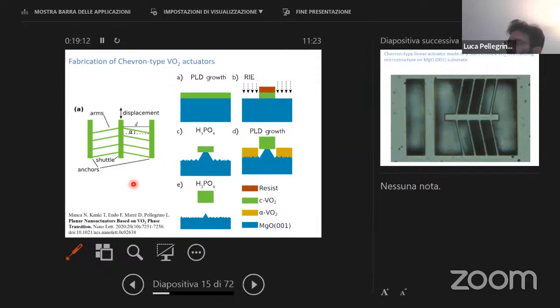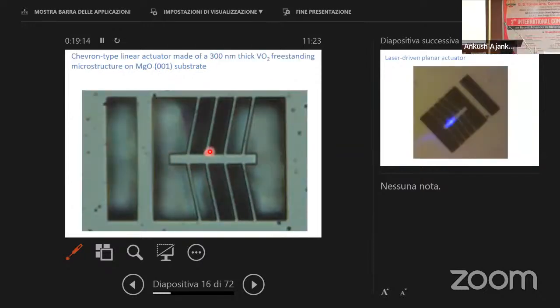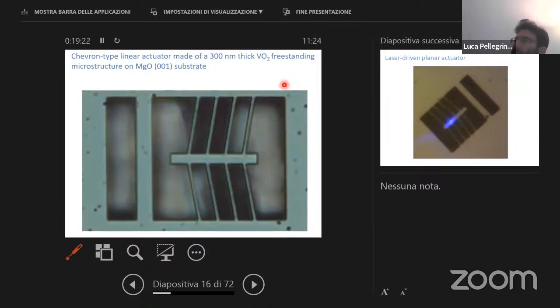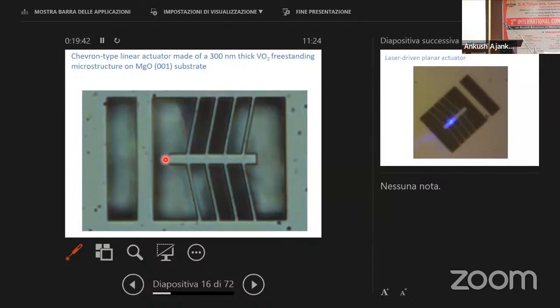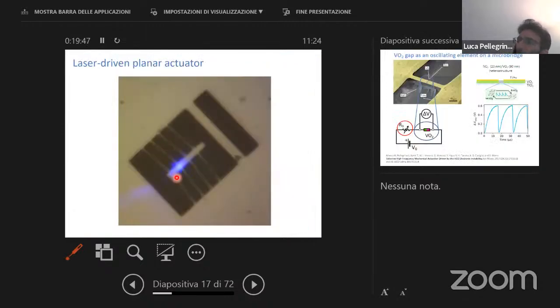The system is moving. These are actuators made below the transition temperature and above the transition temperature. This dimension here is about 20 micron. So they are very tiny structures, which are about 300 nanometers thick. So it's quite thick compared to what is called a thin film in some sense. And you can see this is moving several hundreds of nanometers by heating up the sample, but we can heat the sample even with a laser.